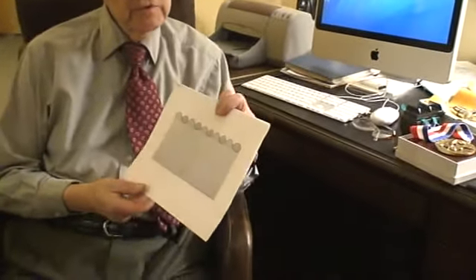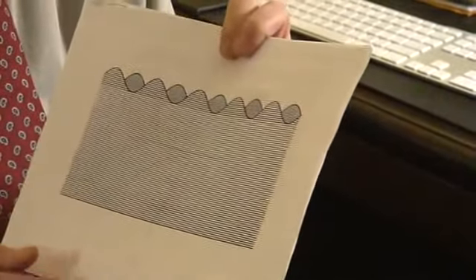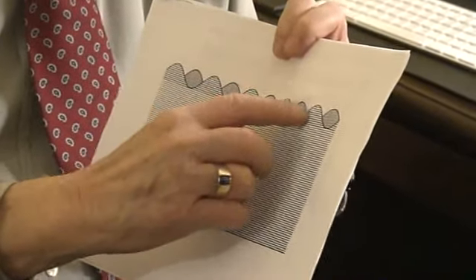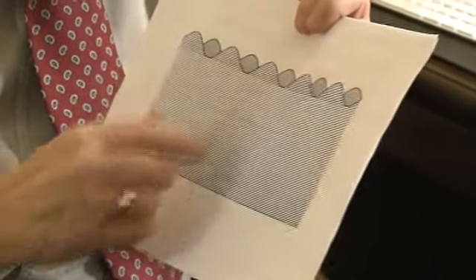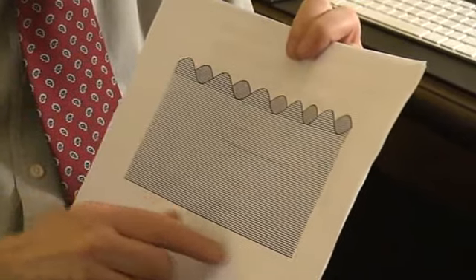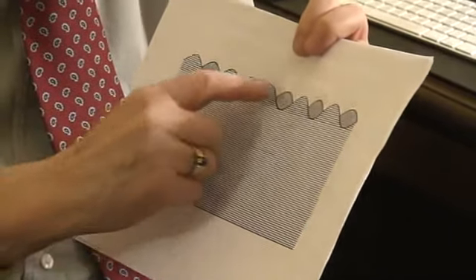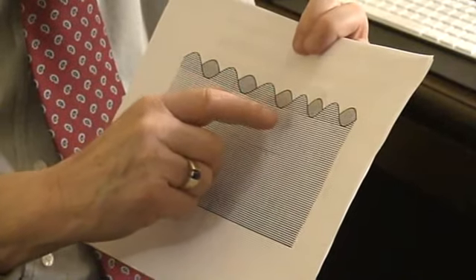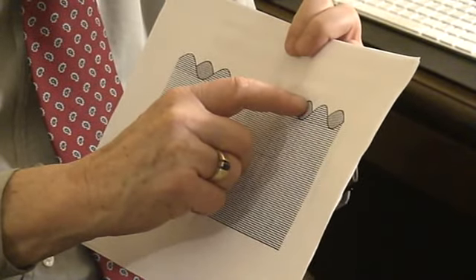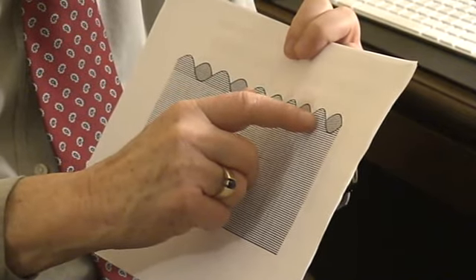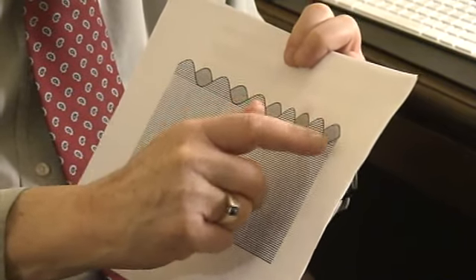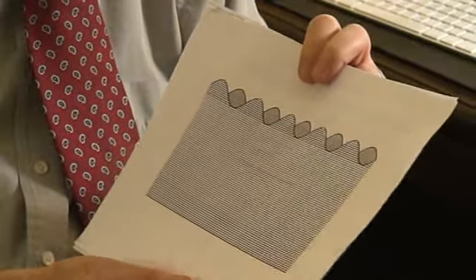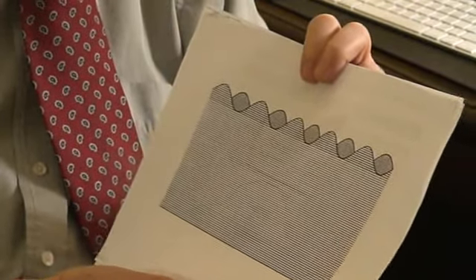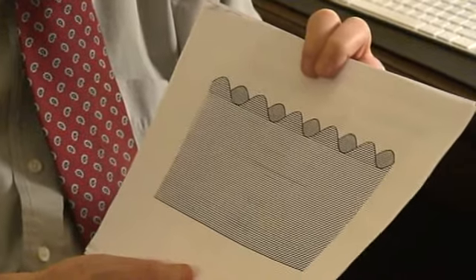We were talking about a new state of conduction electrons in the metal, which corresponds to a spin density wave, where the upspins and downspins both undergo a sinusoidal modulation in density as a function of position in some direction. And shown here is a spin density wave, because here the upspins predominate and here the downspins predominate. So it goes from up, down. And I gave the name of that new state of electrons in metals a spin density wave.